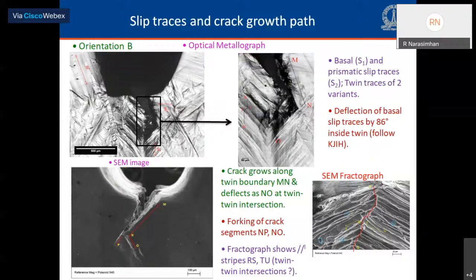And a very interesting feature is, if you follow some of the basal slip traces, take a look at the optical image on the right side top. If you follow the line KJIH, that line deflects by almost 90 degrees inside a twin. And then again, it deflects back by 90 degrees as it exits the twin. So this is due to the lattice rotation inside the twin, and this suggests strong secondary slip activity taking place inside the twins.